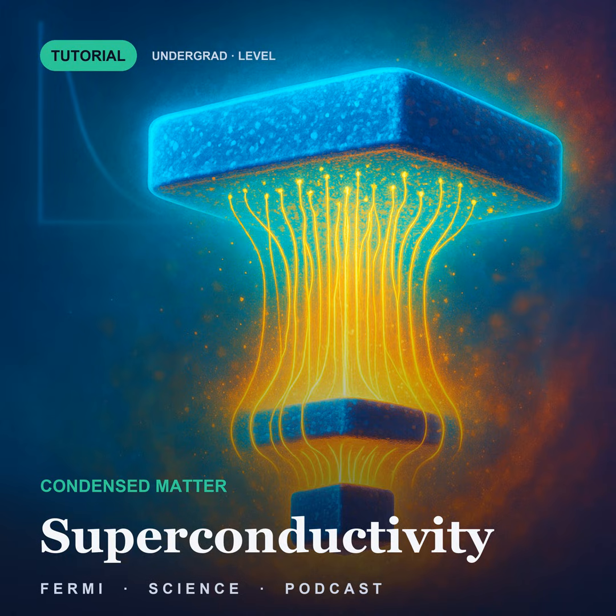Two things happen over that wall, over different distances. The order parameter has to climb from 0 to its full value, and that takes a coherence length, over which you are paying because you have not got the ordering energy yet. The magnetic field has to die from its full value to nothing, and that takes a penetration depth, over which you are gaining because you have not yet paid to expel it. So it is a race between a length over which the wall costs and a length over which it pays.